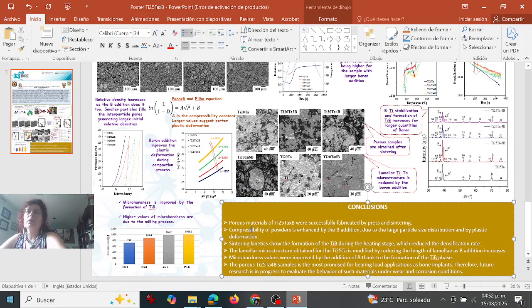All right, if we have a look at the microhardness test and the results we obtain, what we could observe was that microhardness is improved by the formation of titanium boride, and we also obtain higher values of microhardness that we concluded are due to the milling process. Well, let's have a look at the final conclusions.